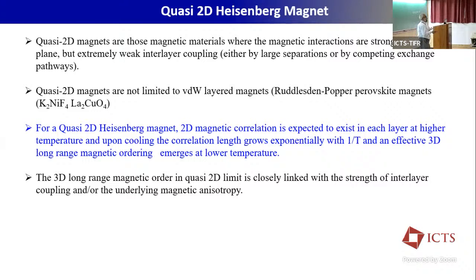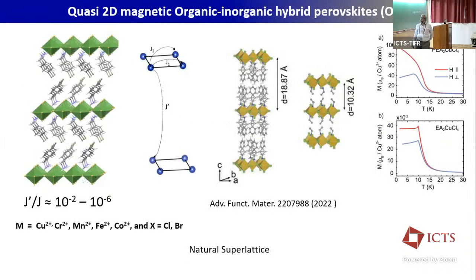So how does the ordering happen in a quasi-2D Heisenberg magnet? This is what we understand. For a quasi-2D Heisenberg magnet, the 2D magnetic correlation exists in each layer at higher temperature. As you cool the system, the correlation length grows exponentially with 1 by T, so that the interplanar interaction leads to effective 3D long-range ordering as you cool down the system. Basically, the 3D ordering in this kind of quasi-2D system depends very much upon the interlayer coupling and the anisotropy present in the system.